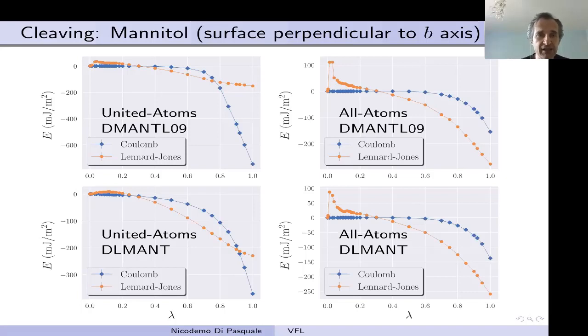And if we integrate these curves, assuming these transformations are reversible, so we can go back and forth and get the same curves, which in this case they are, and they have been tested going from 1 to 0 and then from 0 to 1, when we integrate these curves, we get contributions to the surface free energy. And you see that the curves do look different depending on whether you use united atom or all atom. We also have two different structures from the Cambridge database, DMANTL09 and DLMANT, and you can see some differences there.